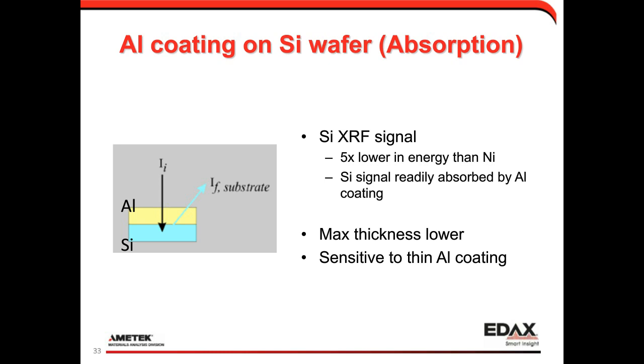elemental absorption edge. So it means that the silicon signal is very readily absorbed in the aluminum coating layer. What this amounts to is that our maximum thickness cutoff for measuring in this configuration is going to be much lower than if we were looking at nickel. And we should have much better sensitivity for thin aluminum coatings, because the silicon is much more responsive to the change in a thin aluminum coating.